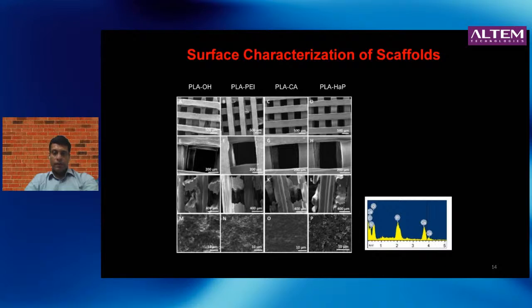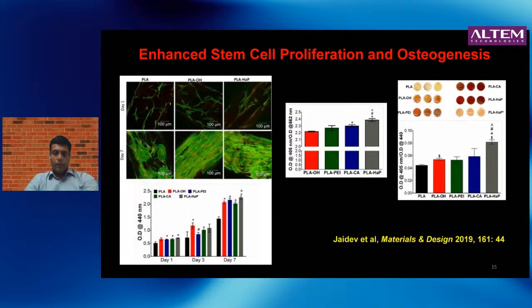So what you can see here is the porous structure of the scaffold at increasing magnification. The last row is zoomed in onto an individual strut of the scaffold. And here on the last bottom corner, you can see the white specks, which is the calcium phosphate that's been deposited on the surface. So then what we did was to take mesenchymal stem cells from the bone marrow. So all of our bone marrows have these stem cells, and their role is to turn into bone-like cells. And we had isolated them.